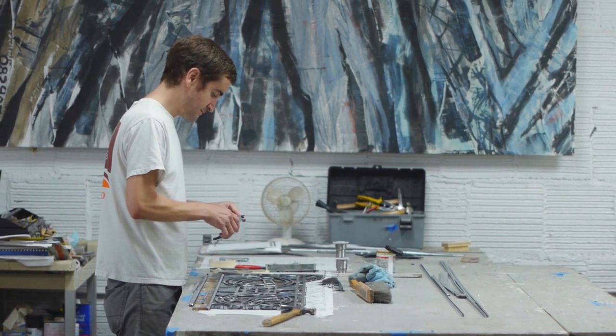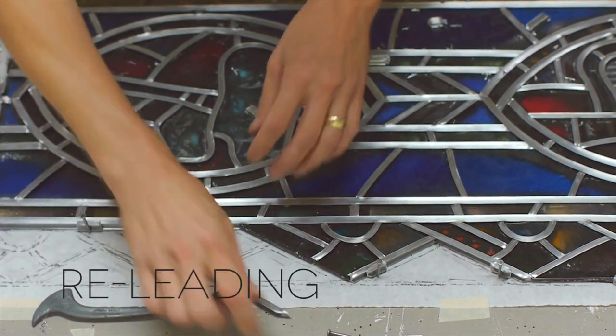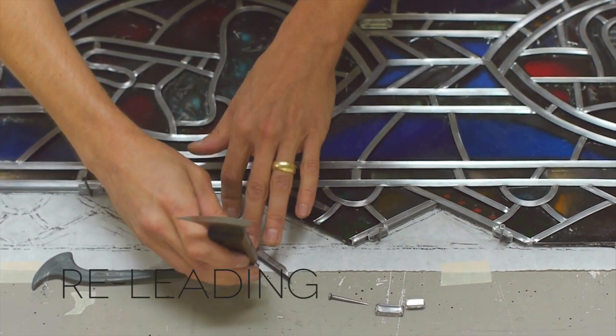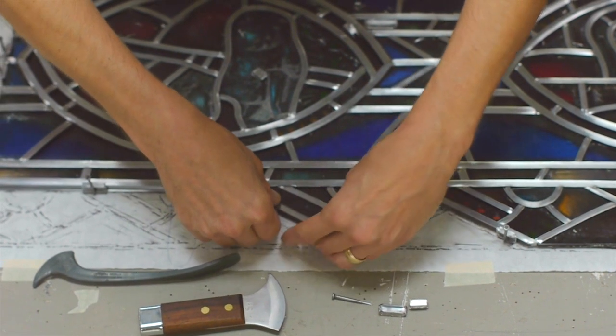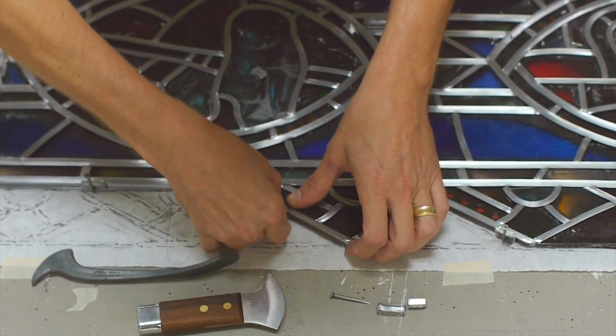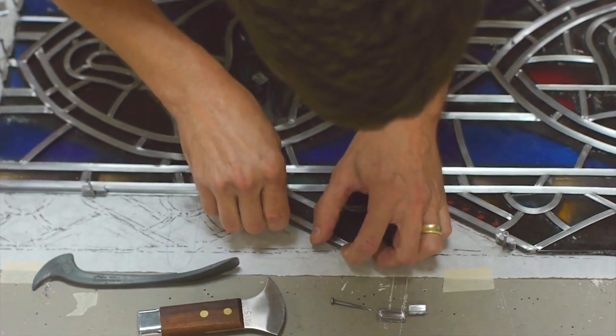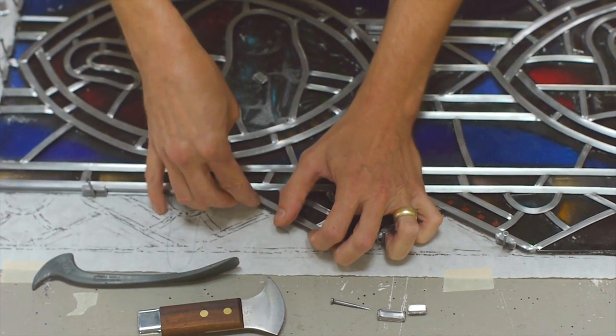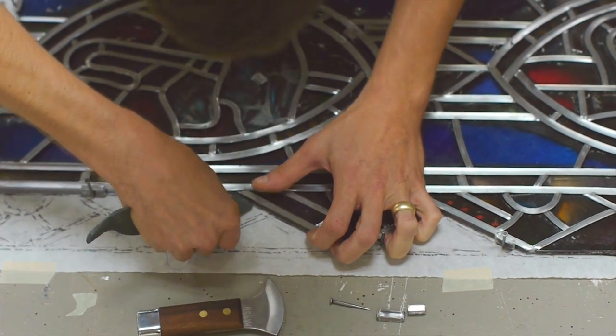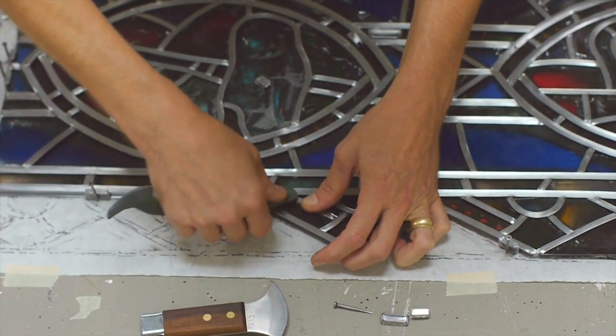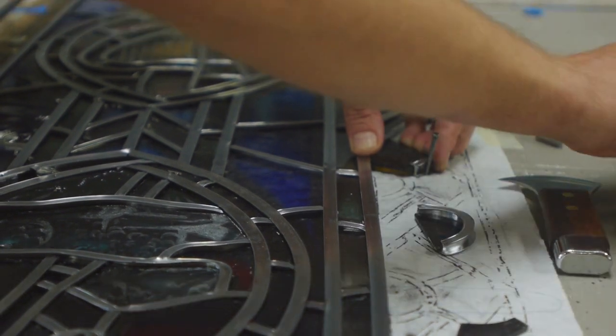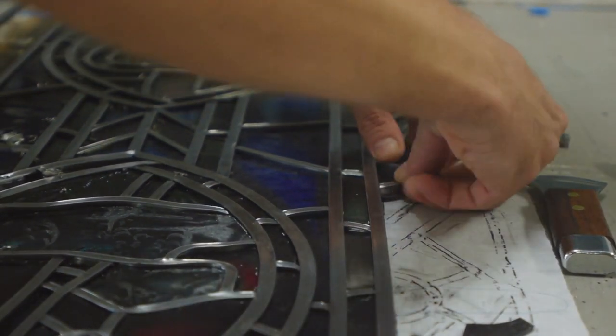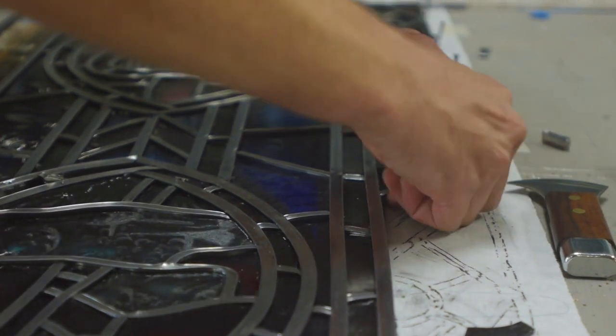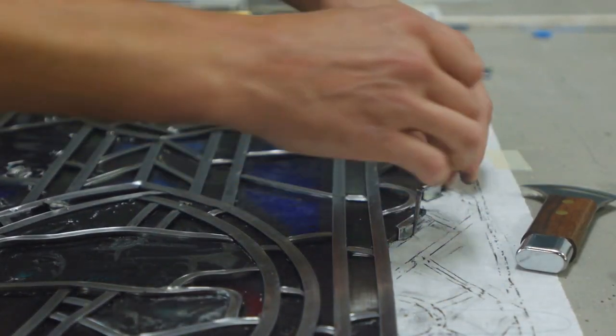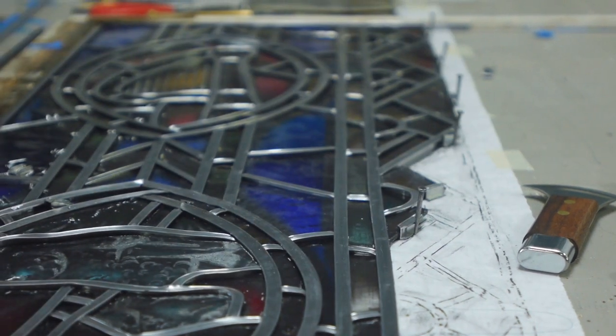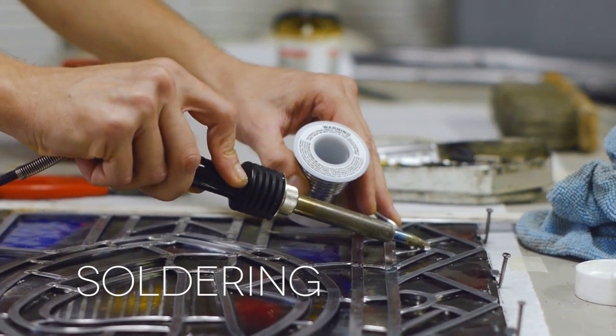When we start to look closely at Marsh's lead work, you can see that he's overlapping the leads, and the overlapped leads is a characteristic of German-made windows, so we will reassemble the windows using the same leading techniques, where we tamp down the ends of the leads and they can be overlapped with the crossing lead to make a much stronger window. You can see here that the leads are standing up very high. After the windows are cemented, another tool will crimp the leads down to the glass, which is also part of the original German technique. So the next step, which is also very time consuming, is soldering the joints.